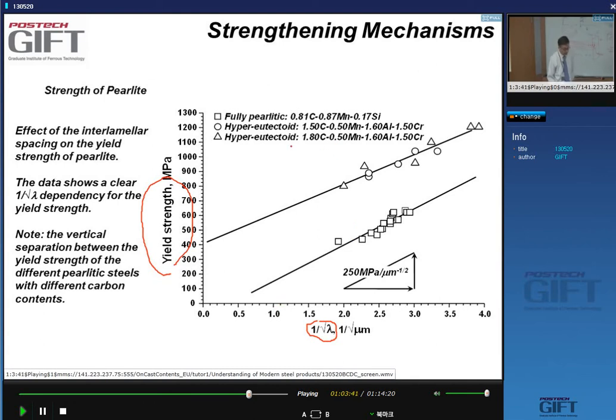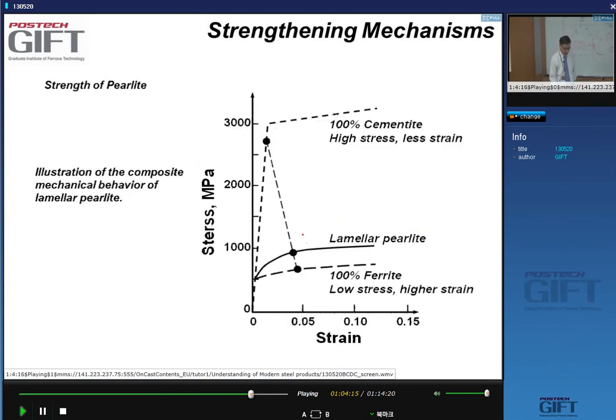So in this particular case, this is a fully pearlitic steel, that means it has 0.8% of carbon. Why do the 1.5 and 1.8% carbon steels give me this equation? Well, that's very simple. That's because there's more carbon. More carbon means there's more cementite in the pearlite, and that gives me this higher strength. So this is just a reflection, but in terms of slope, it's very, very similar.